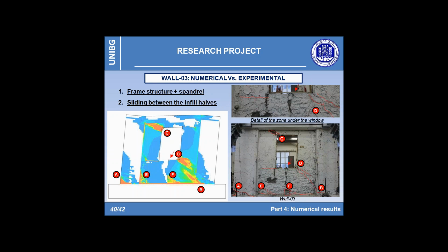Despite it, the last slide shows without any doubt the efficiency of the proposed modeling, comparing the distribution of the strain cracks with an image of how wall 3 looks at the end of the test. The similarities are very interesting. First, with letter A, we can recognize the cracks starting at the base of the shear wall close to the foundation. In the same way, the letter B highlights the damage involving the right wall, where the cracks appear to be less pronounced, probably due to the action exerted by the compressive strut.